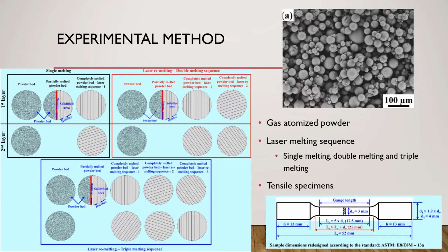Triple melting follows the same process as double melting, but before adding the second layer of powder, the solidified part is scanned again a third time with a hatch-style rotation to remelt it. After solidification, the next layer of powder is added and the process iterates until it is done. These three processes were used to create tensile specimens that served to execute the experiments.